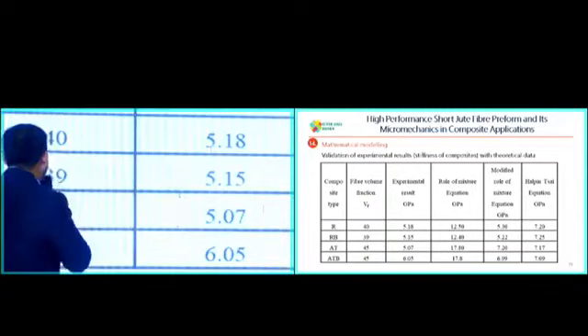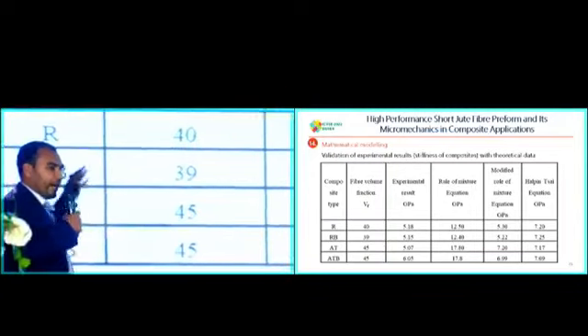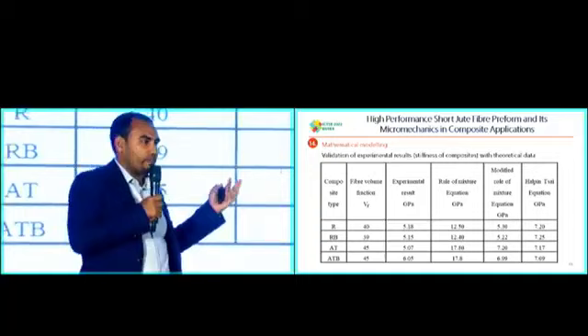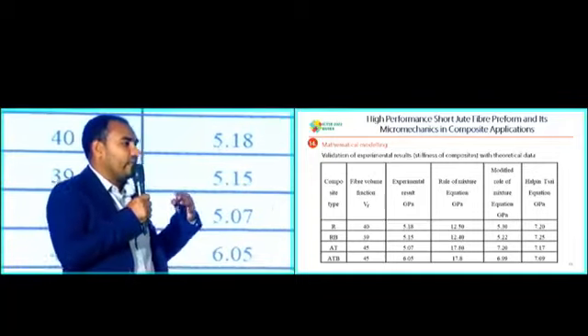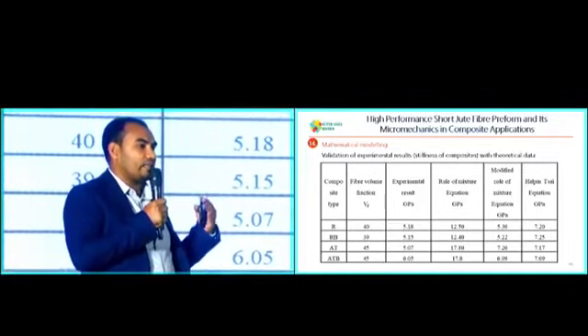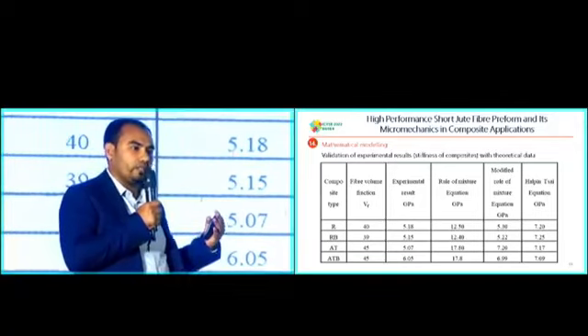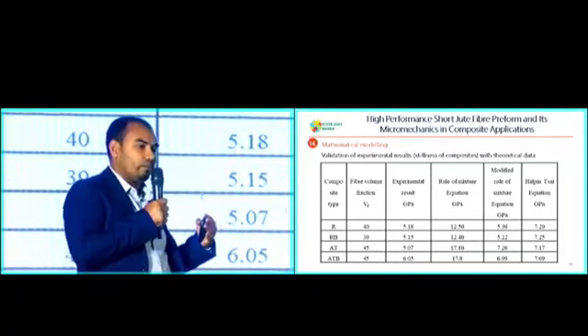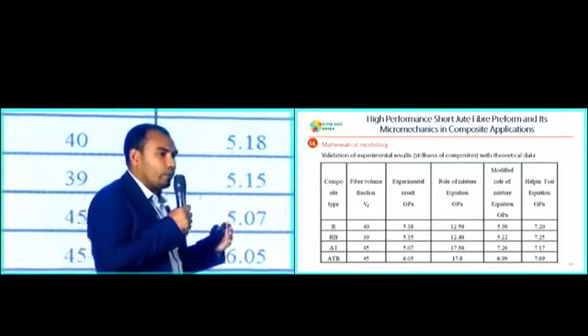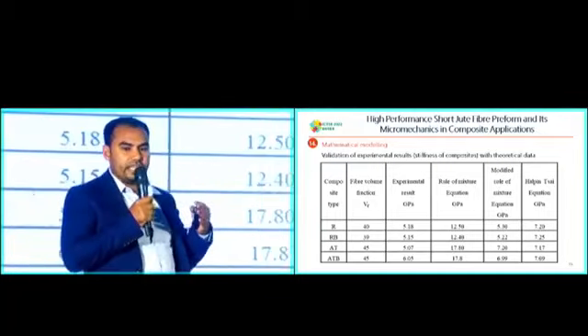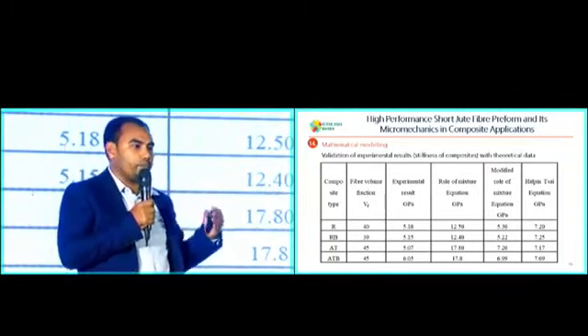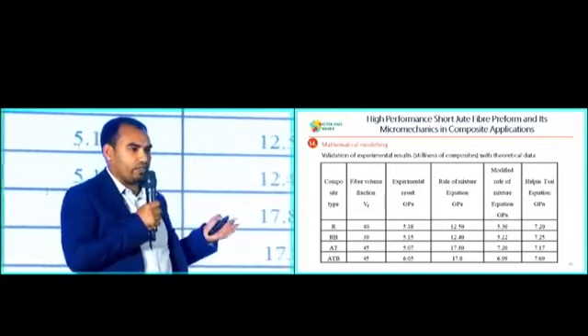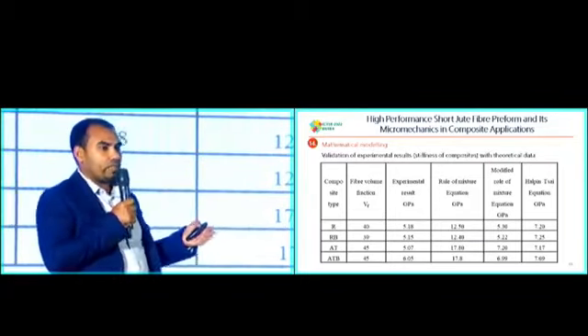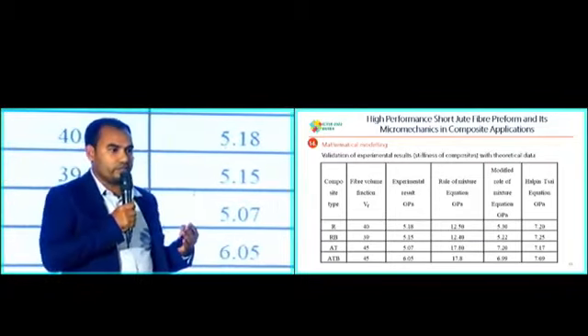It remains the same because the variable cycle cannot change, okay? But experimentally, what is happening is that when you use binders, they increase the fiber volume fraction, but it doesn't give you that much in mechanical properties when arranged in the preform, okay? So the interaction between the matrices and the fiber, that means the interface, may be poor because the binder is applied on the surface of the fibers. As a result, the load carrying ability may be reduced. So this might be the reason.